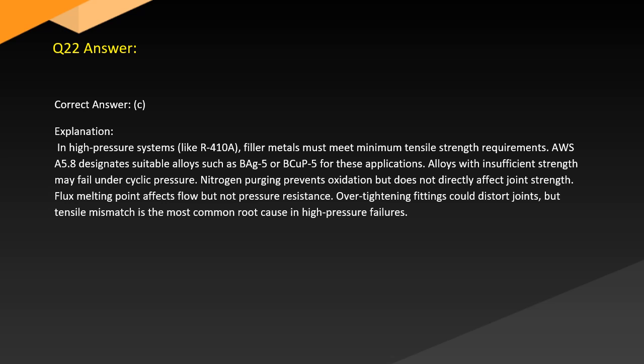Answer. Correct answer: C. Explanation. In high-pressure systems like R-410A, filler metals must meet minimum tensile strength requirements. AWS A5.8 designates suitable alloys such as BAg-5 or BCuP-5. For these applications, alloys with insufficient strength may fail under cyclic pressure. Nitrogen purging prevents oxidation but does not directly affect joint strength. Flux melting point affects flow but not pressure resistance. Over-tightening fittings could distort joints, but tensile mismatch is the most common root cause in high-pressure failures.